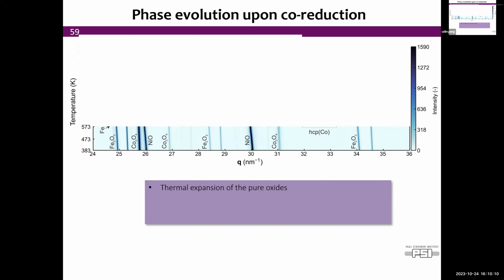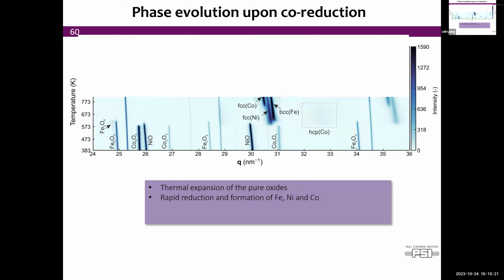So at first we have the 4 oxides. And you see that it's slightly canted here. So this is the thermal expansion of the materials, which changes the lattice spacing. Then we have rapid reduction and formation of iron, nickel, and cobalt. So the oxides disappear. You see they're gone here. The iron oxide is gone. And instead we have BCC iron, FCC nickel, and FCC cobalt. So those are individual particles that are reduced.